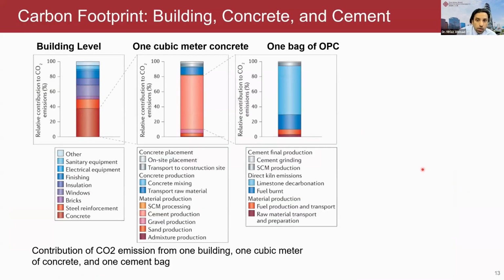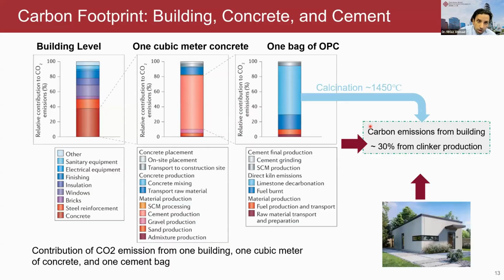Here I have a further breakdown of the carbon footprint from cement and concrete. If we talk at a building level, concrete is a major contributor. If we further zoom into just 1 cubic meter of concrete, we can see that the production of concrete is majorly dominated by cement. And if we magnify it to 1 bag of cement, we can see that most of the carbon emission from the cement comes from calcination, heating the limestone at very high temperature, normally 1450 degrees centigrade. And overall, if we construct one room, around 30% of carbon emission comes only from cement.